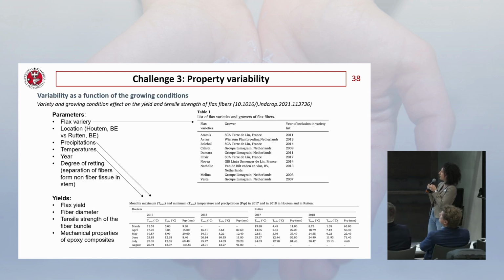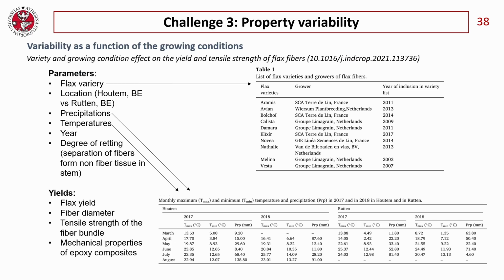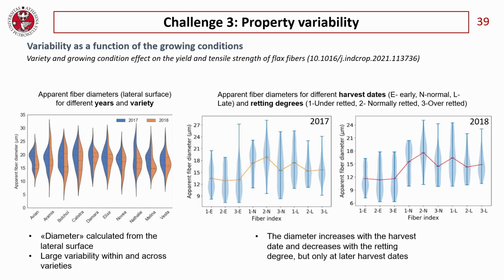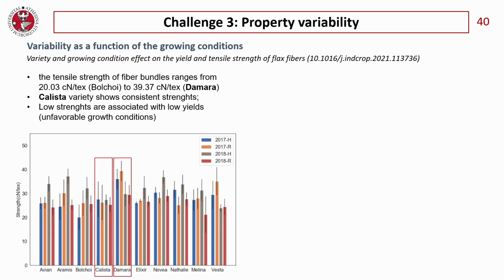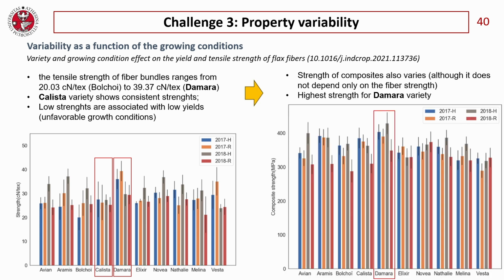Lastly, the property variability. We observed a variability as a function of the growing conditions. For example, this study involved several types of parameters, like the flax variety, the location, the precipitation, temperatures, the year of growth, the degree of retting, and they measured other parameters like the flax yield, the fiber diameter, etc. They noticed a massive effect of the non-controllable parameters like moisture, precipitation, or temperature during that year on properties like the diameter of the fibers and finally the tensile strength of the fibers and also, of course, the tensile strength of the composite.